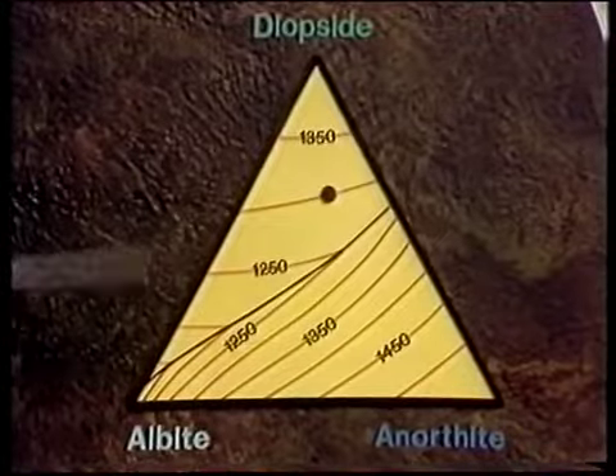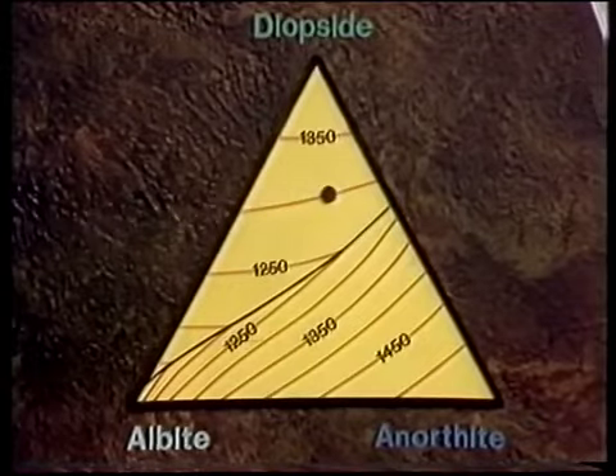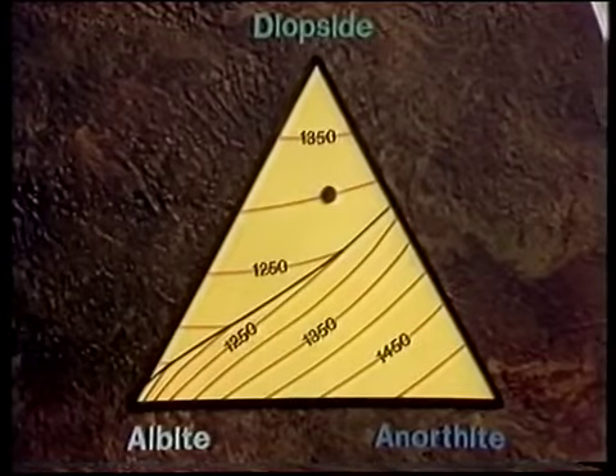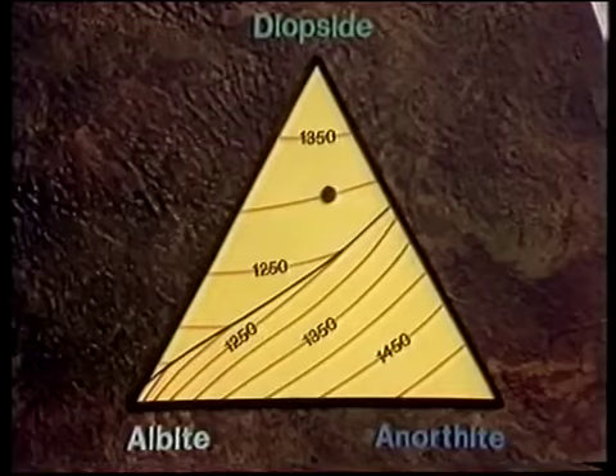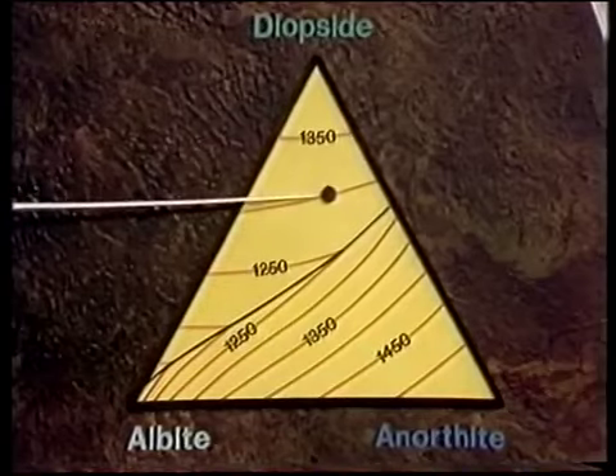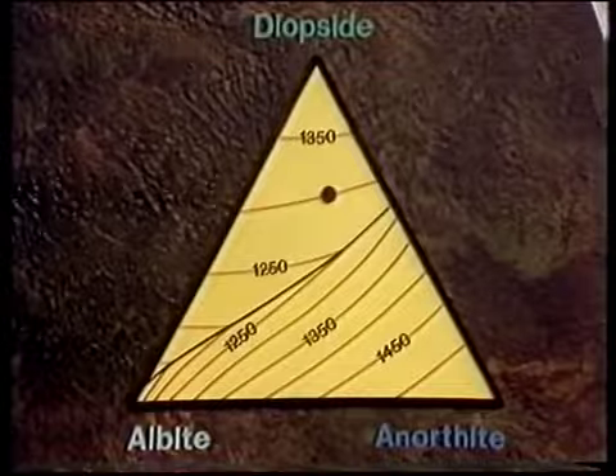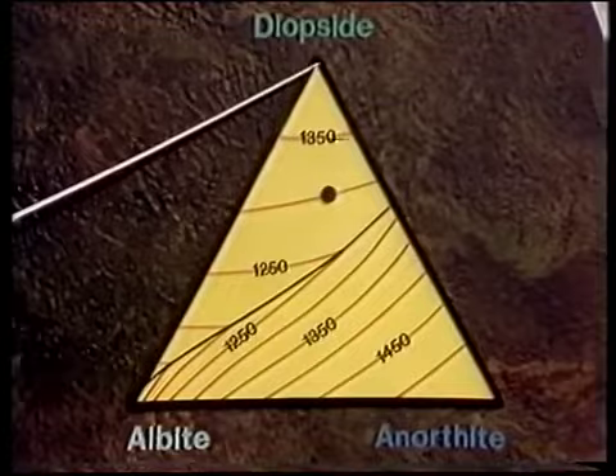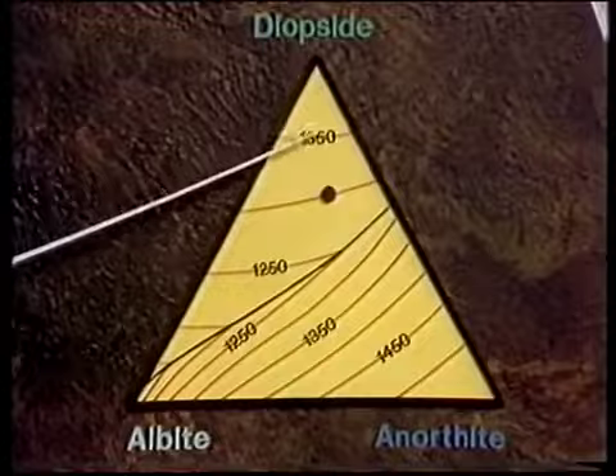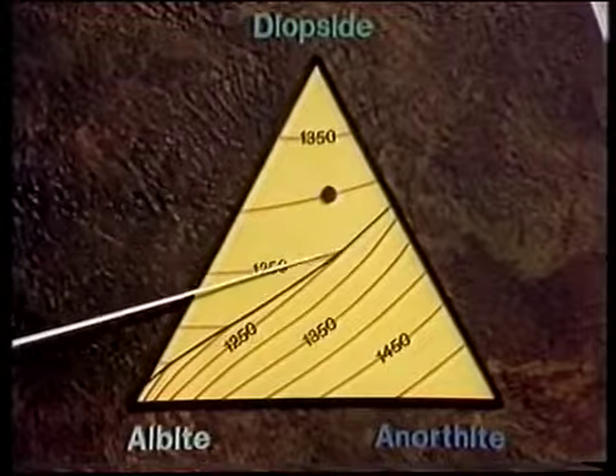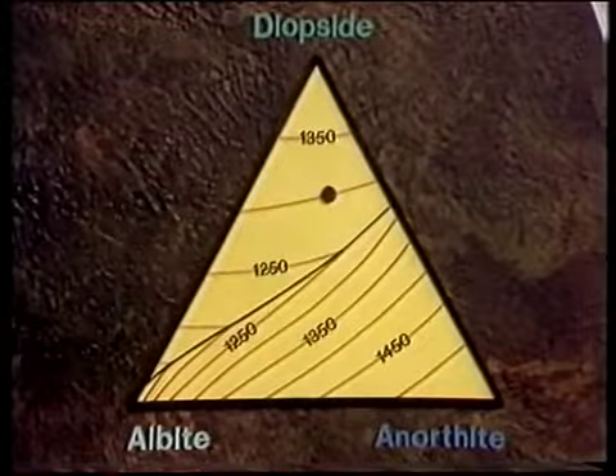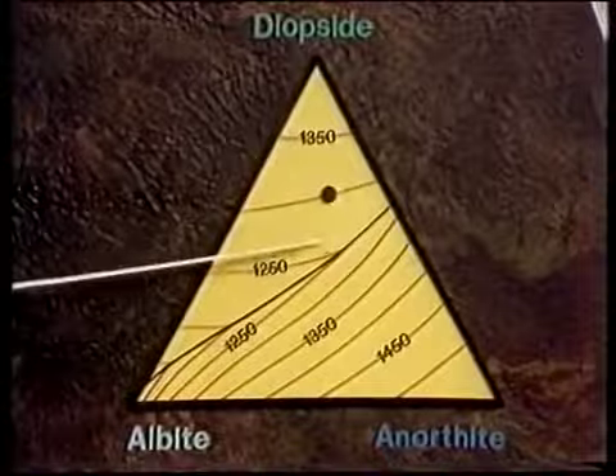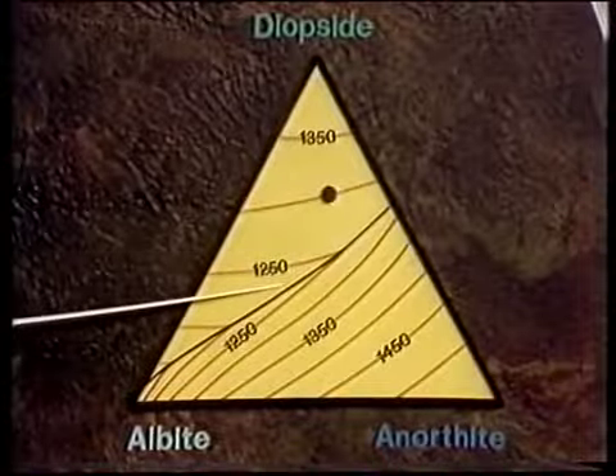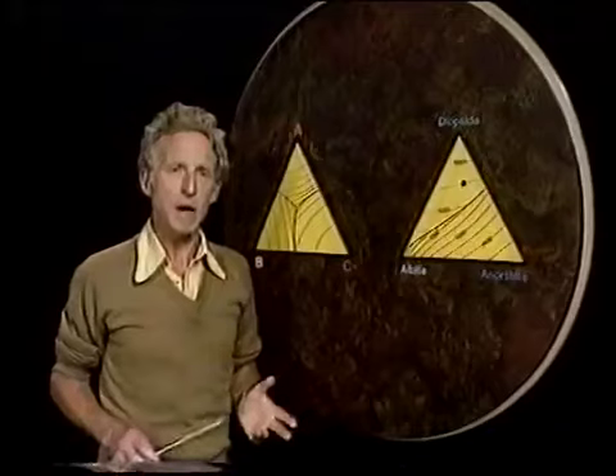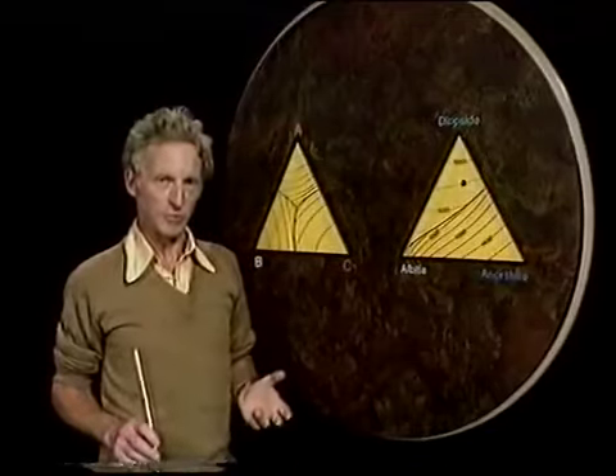Now let's see what happens when a melt of this composition cools. It's about 60% diopside, 25% anorthite, and about 15% albite. When it cools, it'll intersect the liquidus surface at 1300 degrees centigrade. And crystals of diopside will begin to separate. That will drive the melt away from the diopside corner down to the cotectic. At that point, a second phase has to crystallize, and the liquid has to move down the cotectic in that direction. That can only happen if anorthite is removed as well as diopside.